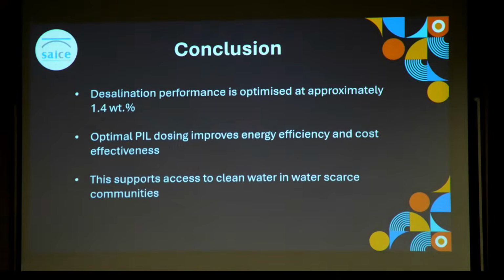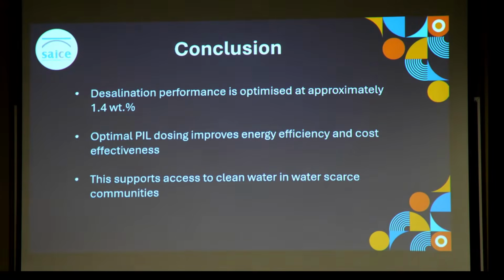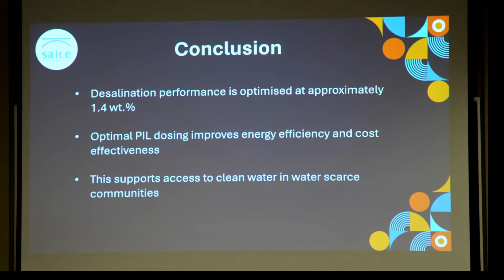In conclusion, our results confirm that there is an optimal concentration of PIL at which desalination performance is maximized. This optimum is observed at approximately 1.4 percentage weight, beyond which further PIL becomes counterproductive.